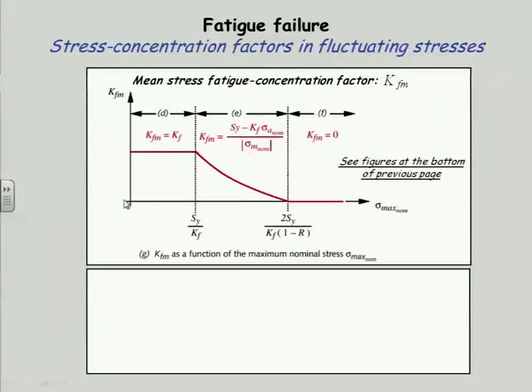And if I plot these 3 regimes, this axis is the maximum value of stress. And right here, this dotted line represents the value of SY divided by KF. We're going to apply the KF to the calculation because we have the stress. We know we have a stress concentration, and I want to know, does that stress in the stress concentration yield the part locally? So I'm going to multiply the maximum stress by the K sub F and compare that to the yield strength. Did I yield at the end of the crack is the question. If I don't, then I'm going to use the full KF for KFM because I never yielded. But if I start to yield it, then I'm going to work this down until when I get to twice SY, which means that I'm exceeding it at both ends, I now in effect have a fully reversed case, and I'll knock it down to 0.